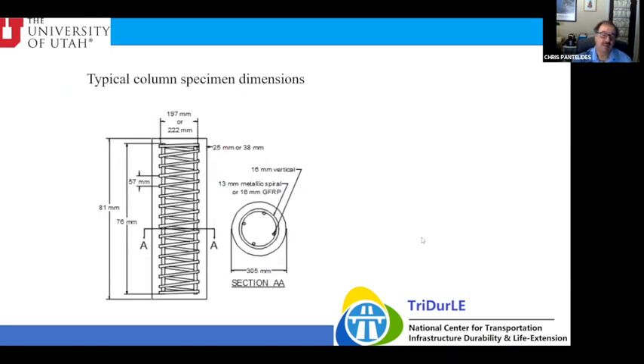So then we constructed typical column specimens similar to the one we had done before. The diameter of the column was the same, at 305 millimeters. But the diameter of the spiral varied a little bit because we used a little larger fiberglass spiral compared to the metallic spiral. Metallic spiral here is only the stainless steel bar. The stainless clad bar does not exist in spiral form, only longitudinal form.